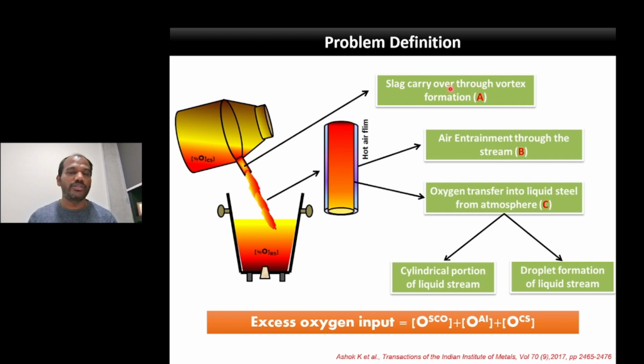Through vortex formation, the slag carryover takes place, and as soon as the liquid steel stream is exposed to the atmosphere, you can see that the stream will be attached to a hot air film, and atmospheric air will be entrained through this stream, and there is oxygen and nitrogen transfer into the liquid steel from the atmosphere. This is the second phenomenon that is taking place when the stream is exposed to the atmosphere.